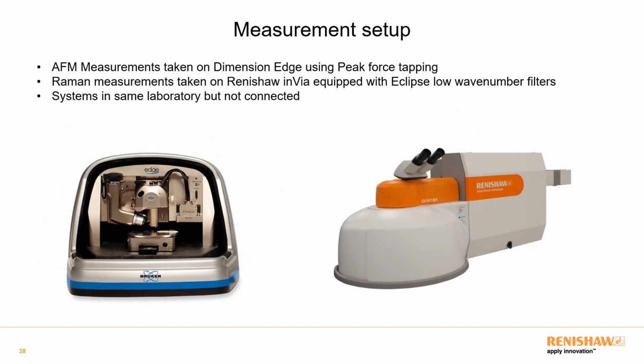In this work, I have done this. I used two instruments: a Bruker Dimension Edge AFM, using PeakForce Tapping to identify the layer thickness of some rhenium disulfide flakes. I then used a Renishaw inVia Qontor Raman microscope equipped with Eclipse low wave number filters. This enabled me to measure the Raman bands even very close to the laser line. The same system was equipped with Rayleigh scattering filters, which I'll talk about later as well. So all these experiments were done on these two systems.